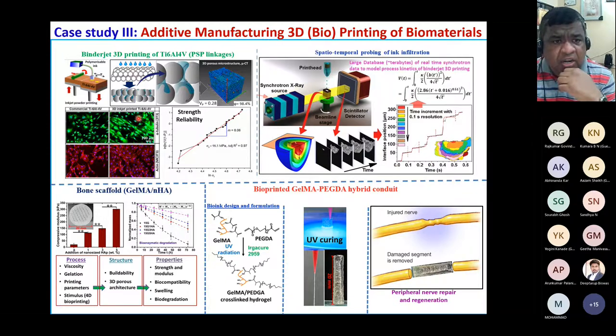Now we have used titanium 6 aluminum 4 vanadium as a model material to implement that new binder formulation scheme. And then what we have found is that we are able to get a very good Weibull modulus, which is kind of a modest number, like 8, for a material which has 28% volume porosity and 98.4% interconnected pores. And these materials also support good osteoblast and fibroblast cell functionality.